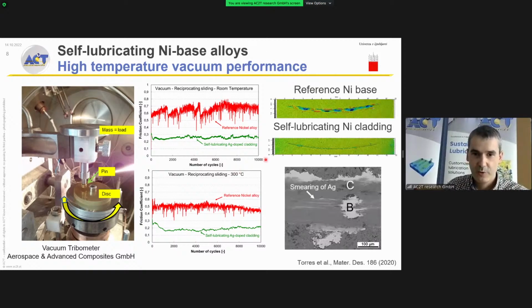And in this case, what we can observe also is that not only the friction is much better, but also the wear is much better. In this case, we have, for the reference, nickel-based cladding, severe plastic deformation, we have an irregular wear track, and we have the self-lubricating nickel cladding. Friction is very, very small, very homogeneous wear scar, and very, very narrow, very thin. And we can see here in the scanning electron microscopy image how this smearing of silver that is supported here by thermal softening at 300 degrees helps and aids in controlling friction at these temperatures.